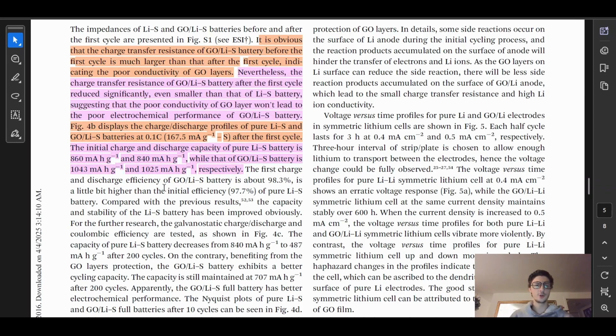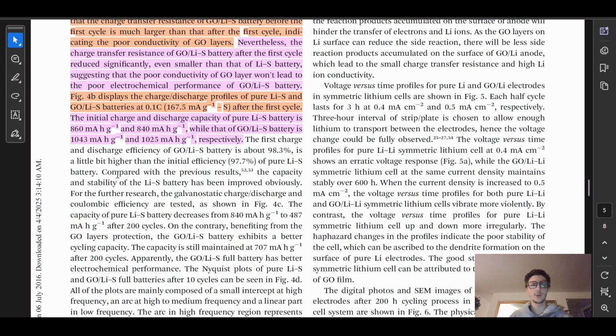The first charge discharge efficiency of graphene oxide lithium is about 98.3%, a little bit higher than the initial efficiency, 97.7%, of the pure lithium sulfur battery. Compared with the previous results, the capacity and stability of the lithium sulfur battery has been improved, obviously. They give the previous results here.